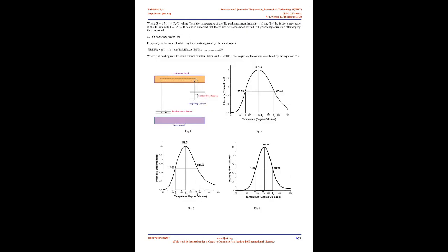The same procedure was adopted for KMgSO4F:Dy and KMgSO4F:Eu. In this case, instead of copper, the sulfate salt of dysprosium or europium was used. Formation of the compounds was confirmed by taking the X-ray diffraction, XRD. The X-ray diffraction pattern of the prepared KMgSO4F material did not indicate the presence of the constituents MgSO4 or KF and other likely phases. These results indicate that the final product was formed in homogeneous form.